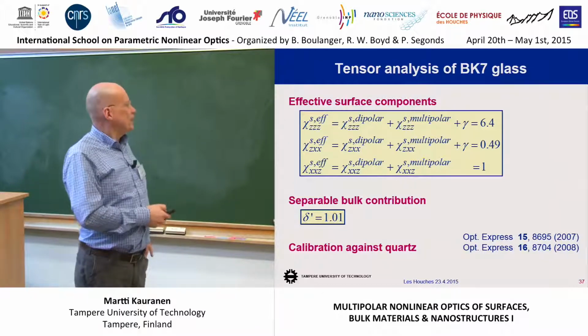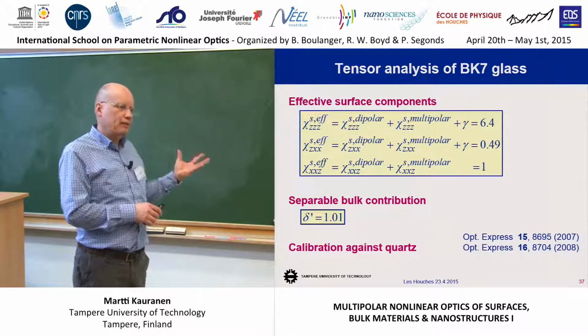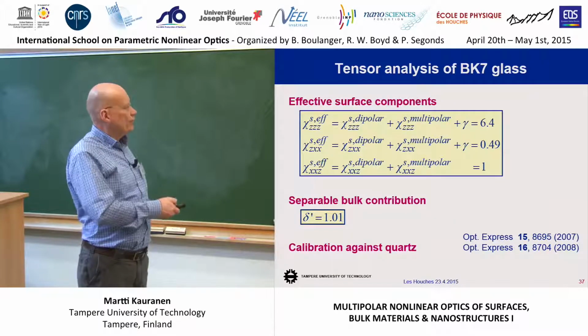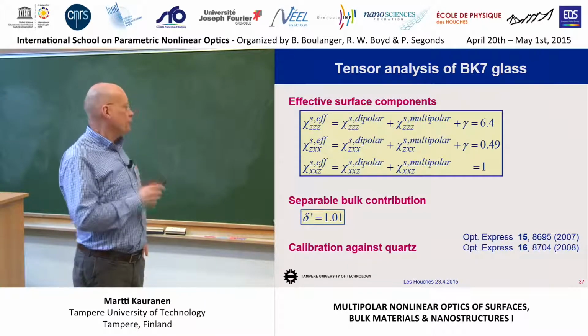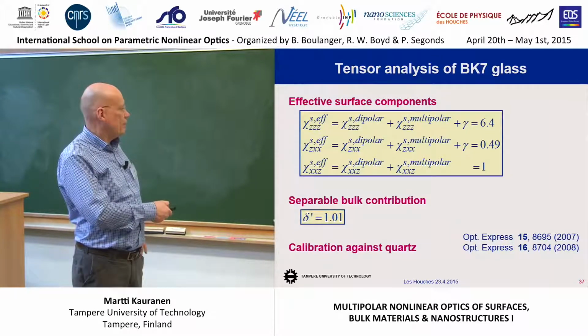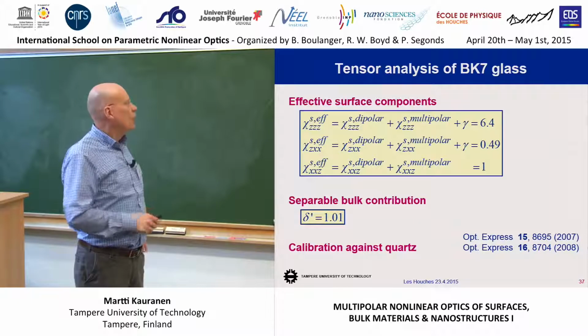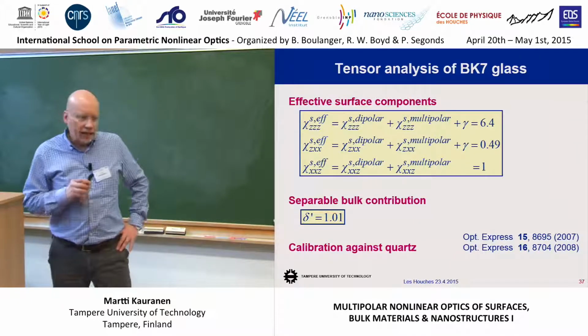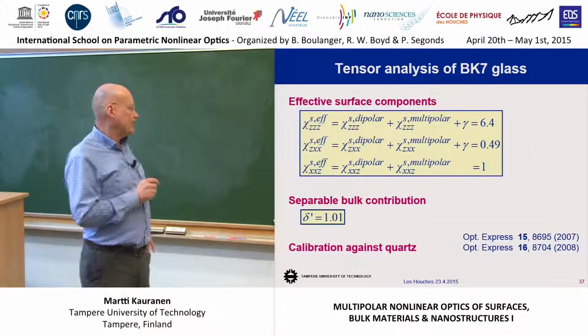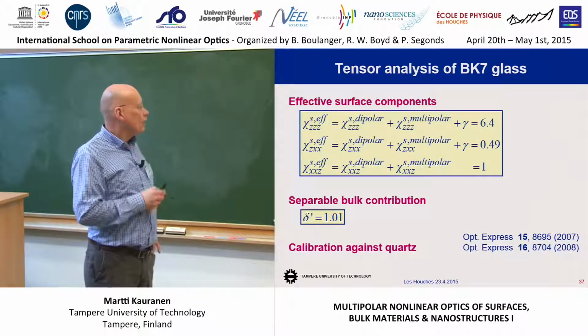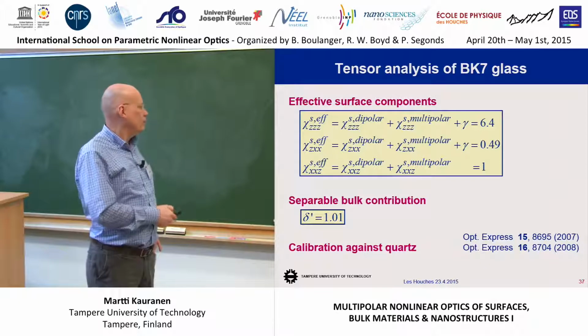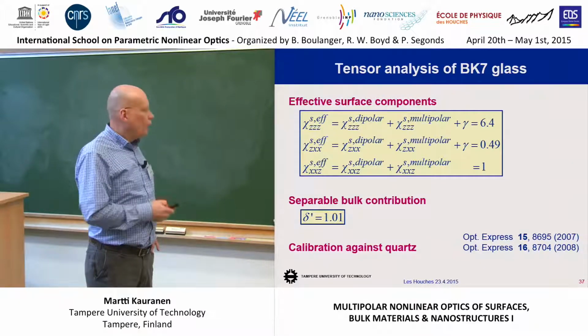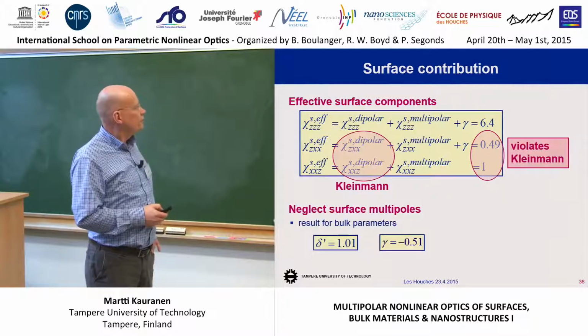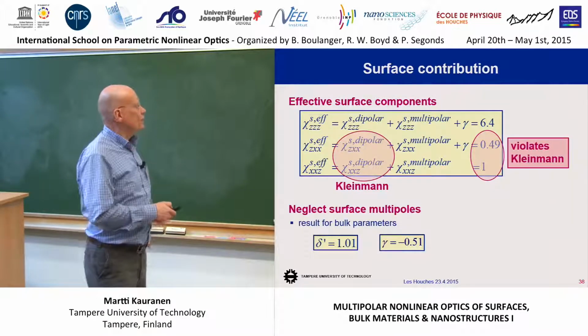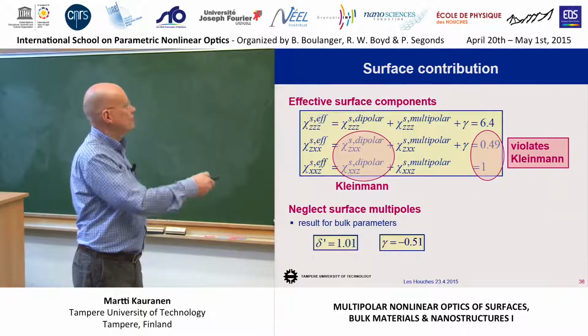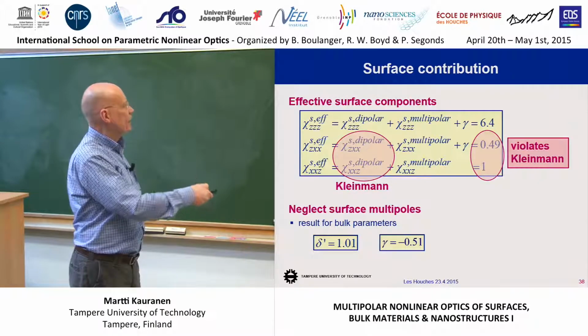And when we do that, in the past, people have measured surface responses, and we have reasonable agreement with earlier measurements. The new thing is that we have been able to access this bulk contribution. And now, let's have a look at whether this really makes sense, what we have measured, and whether we can get a handle on what is the origin of the bulk response. And in order to do that, let's assume that whatever happens at the surface is just an electric-dipole tensor.